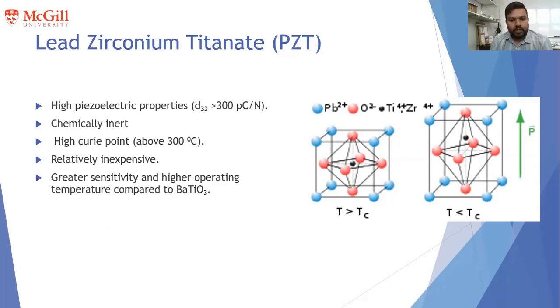Coming to PZT again, it has good sensory properties compared to another most popular piezoelectric ceramic, barium titanate, and it's also chemically inert. The high Curie point of PZT gives an edge in sensory operation at high operating temperatures compared to barium titanate, which has a very low Curie point, around 110 degrees.